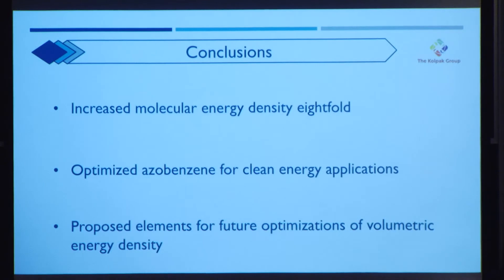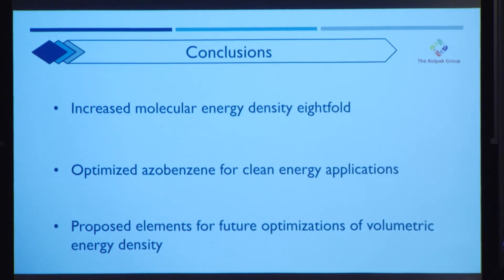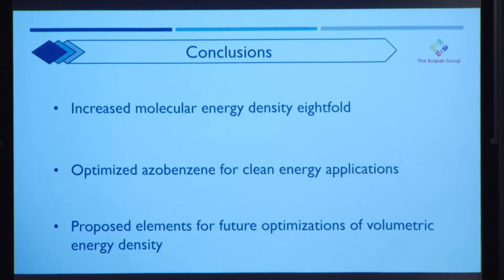In conclusion, our project attempted to increase the molecular energy density of azobenzene as a solar thermal fuel by simulating metallic phosphate frameworks, which are incredibly novel. We were successful — we increased the molecular energy density of azobenzene across all six structural variations, and in some cases, such as the zirconium framework, increased molecular energy density eightfold over conventional values. This represents progress in optimizing azobenzene for clean energy applications and creating a more sustainable energy future. We also propose indium and bismuth for future optimizations of volumetric energy density, demonstrating the potential of azobenzene STFs not only in the lab, but also in the wider world.